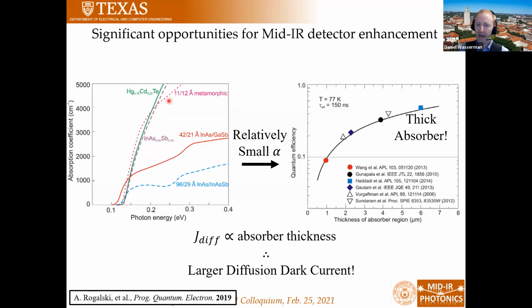So if you look at bulk materials, what you see is a very strong turn on of the absorption. I'm plotting here, this is from a Rogalski paper, the absorption coefficient as a function of photon energy. And you can see that for the type 2 superlattices, you're losing a significant amount of absorption. So they're not nearly as good absorbers. So what does that mean? Well, it's going to affect the quantum efficiency of your device, right?